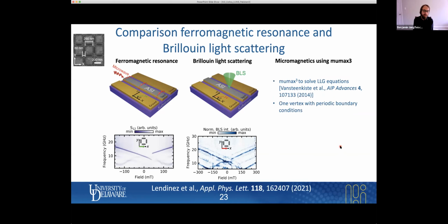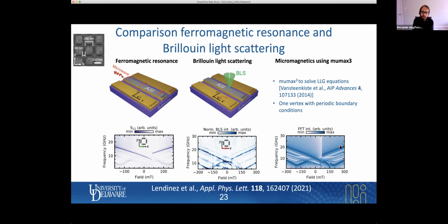Now we can do this as a function of field, just like we did the experiments. And these are the results. We observe here a very good agreement between the modeling and the experiments. I also want to mention that by doing this angular dependence I was just asked about, we found the observation of a mode splitting, where the oscillations reside in different parts of the lattice. If you are interested, I would like to refer you to this paper.